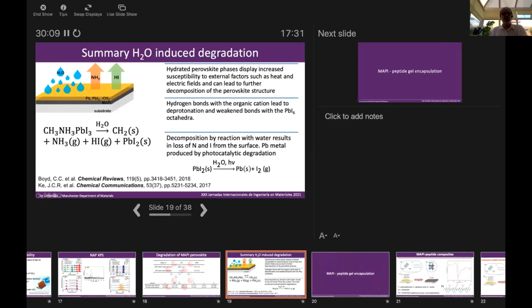So to summarize what we saw, this reaction appears to occur via this process. We have reaction of water, or also vapor, with our methyl ammonium lead iodide. It forms a hydrocarbon. Obviously this should be in brackets with an n. It's an amorphous hydrocarbon. It's not CH2, because that wouldn't exist. And if it was methane or ethane, it would just dissolve from the surface. We also form ammonia gas, which is lost from the surface, and hydrogen iodide gas, which is also lost from the surface. We don't know whether this process would occur if we weren't in a vacuum, but being in a vacuum, if we are forming hydrogen iodide, it's likely to evaporate at these kind of temperatures at the kind of vacuum we're using. And then we're left with lead iodide on the surface.